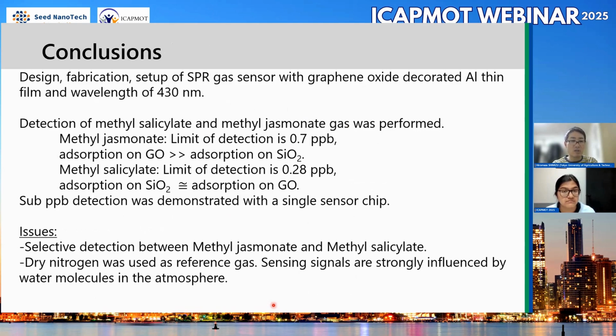So this is a conclusion. We showed the design, fabrication and setup of an SPR gas sensor with graphene oxide decorated aluminum thin film and a wavelength of 430 nanometers. We detected methyl salicylate and methyl jasmonate. The detection limit for methyl jasmonate is 0.7 ppb, and the adsorption on graphene oxide is much higher than adsorption on SiO2. And for methyl salicylate, the limit of detection is 0.28 ppb. The adsorption of SiO2 is comparable to the adsorption of graphene oxide.